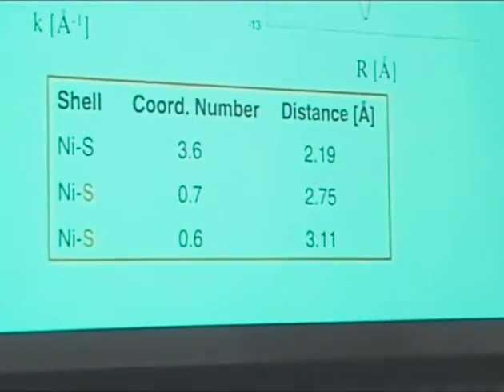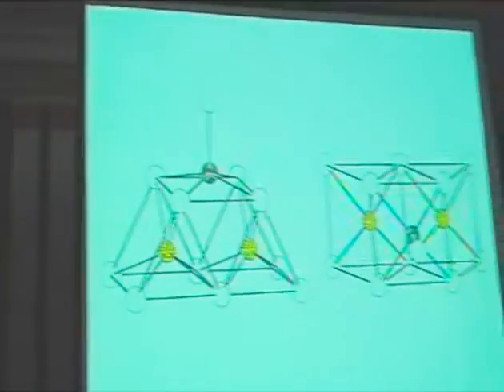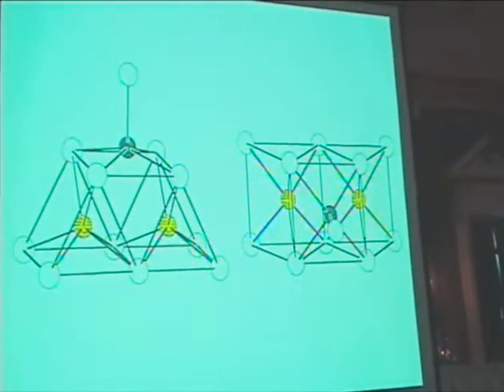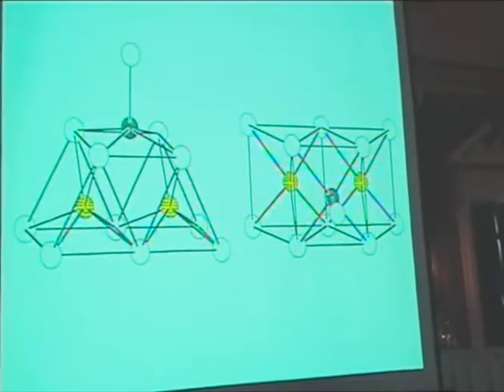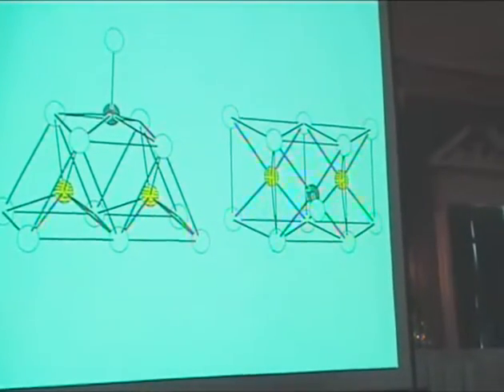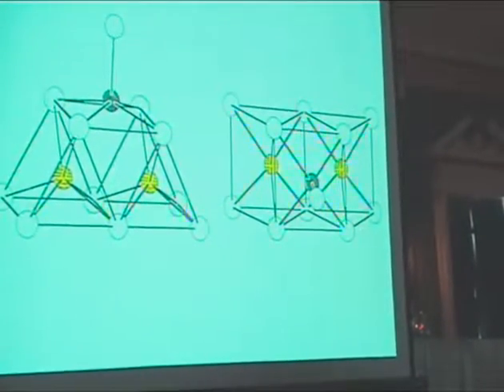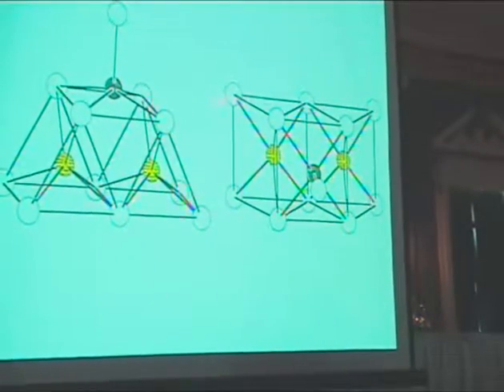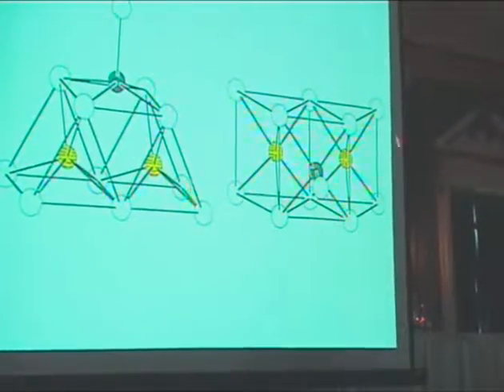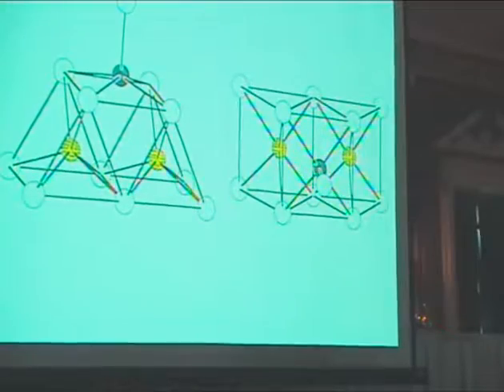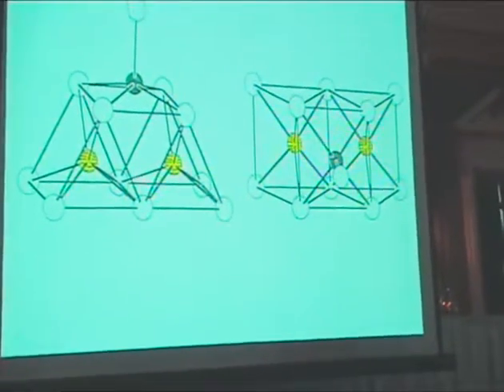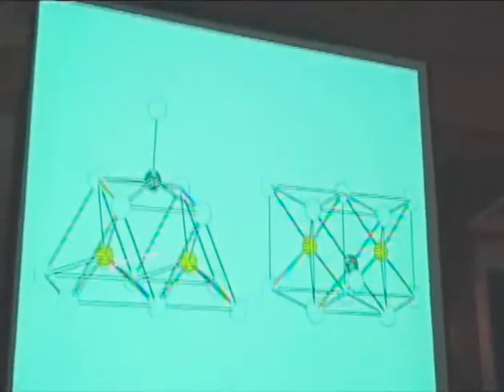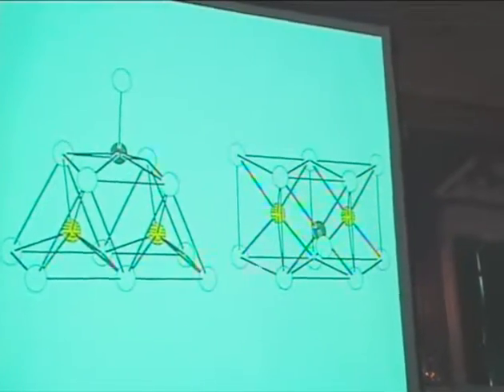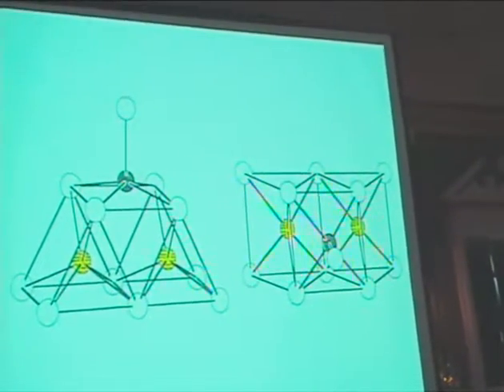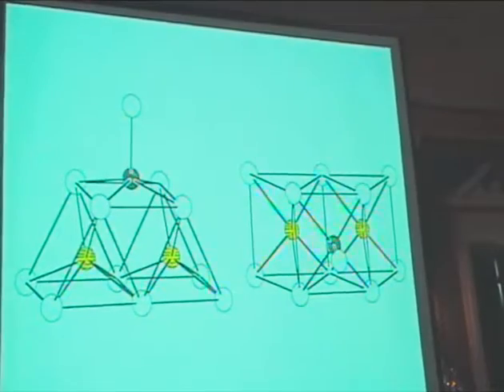And if you now use that information, you might come up with a model like this. Suppose we assume, which we already knew from the Topsoe work, that the nickel or the cobalt is hanging on the edges of the MoS2. And here I have the MoS2 slab with the sulfur layer, another sulfur layer, here in yellow, the molybdenum is in between. Here I've rotated it 90 degrees, so we are looking onto the sulfur plane. And then it's logical to assume that the nickel is hanging on the edge. And where is it then?